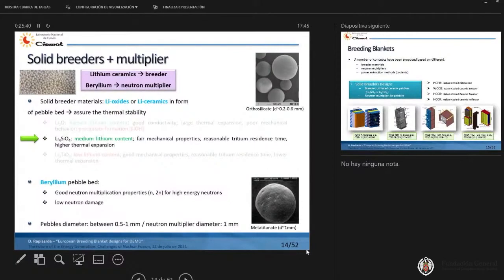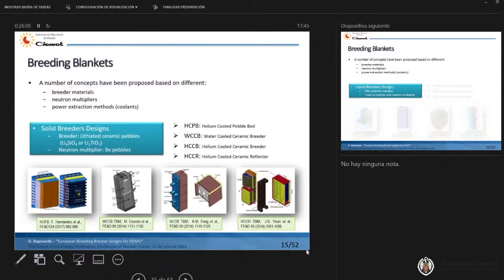Why beryllium? Because it has good neutron multiplication properties for high energy neutrons. I have not put the cross section here, but believe me, it has quite good properties. And quite important also, it has low neutron damage. The pebble diameters are between 0.5 and 1 millimeter for the breeder and about 1 millimeter for the neutron multiplier.